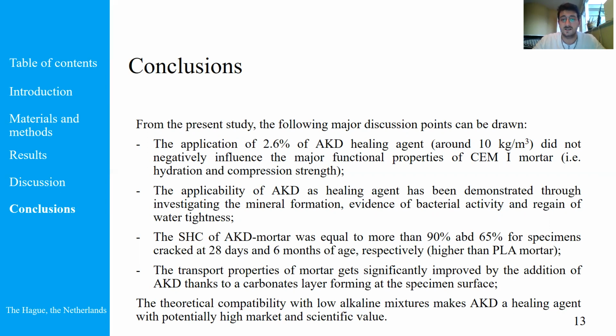That the self-healing capacity of AKD mortar was equal to more than 90% to 65% for specimens cracked at 28 days and 6 months of age, and that it was higher not only than PLA mortar specimens, but also than the positive reference specimens, and that the transport properties of mortar get significantly improved by the addition of AKD, thanks to a carbonate layer forming at the specimen surface. And also, as a potential benefit of this application, the theoretical compatibility with low alkaline mixtures makes AKD potentially of high market and scientific value.